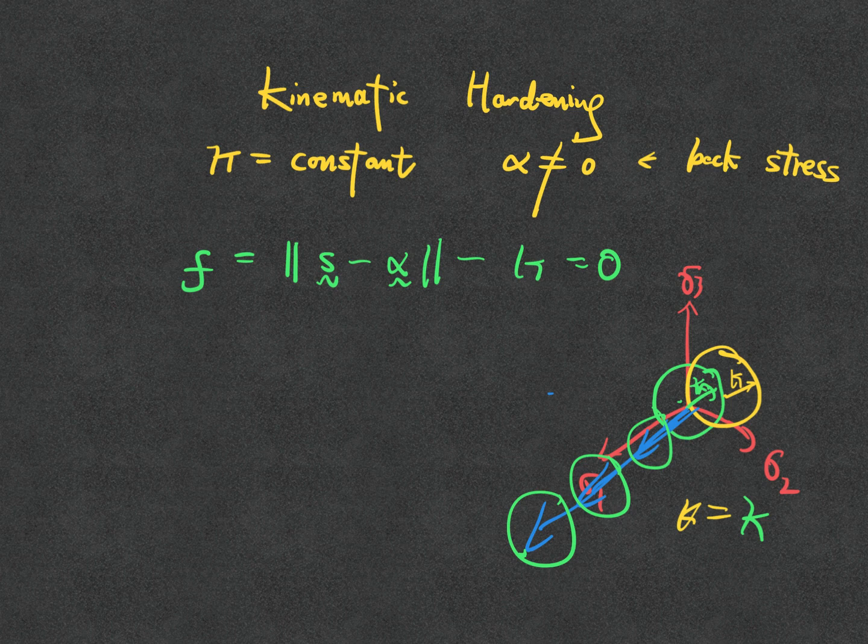You can think about isotropic hardening sort of like a balloon. I can push more air in to make the yield surface bigger and bigger so that the tip of the arrow is just touching the boundary of the balloon. Okay, does that make sense? And then the kinematic hardening is like a rigid ring on the pi plane where the radius is fixed, but as I push the boundary, the yield surface keeps moving. So that geometrical interpretation can help you think about how to implement it.